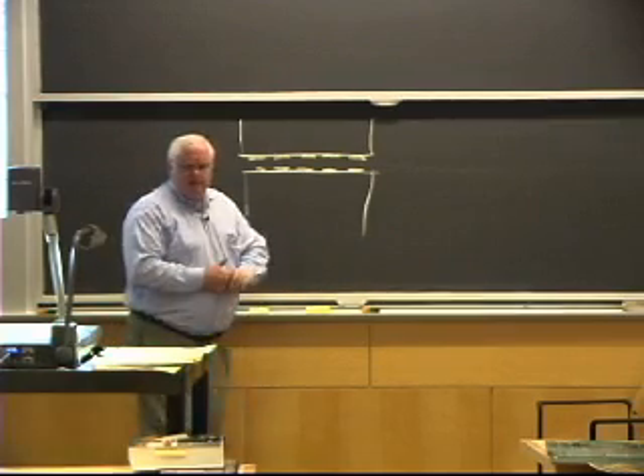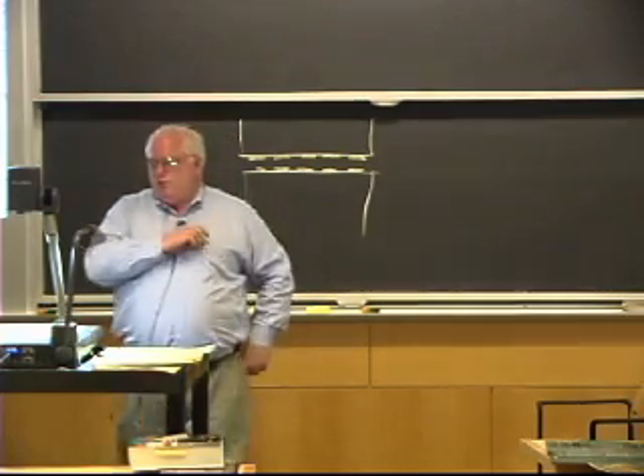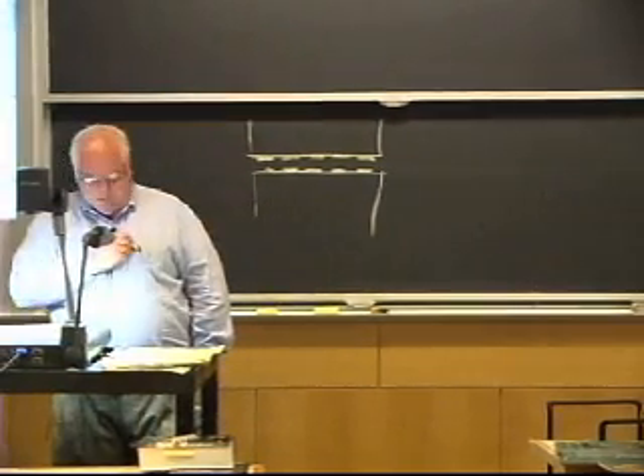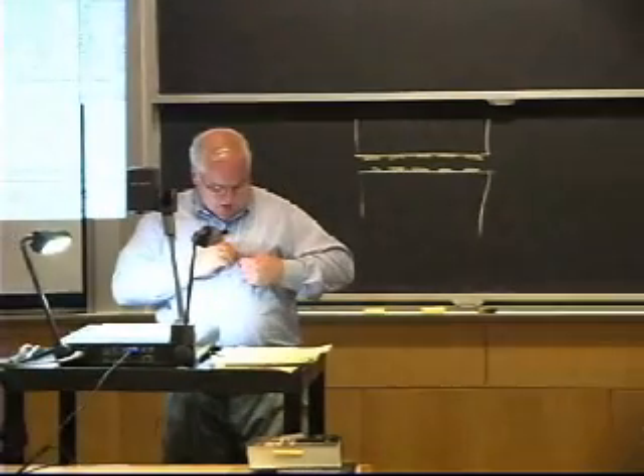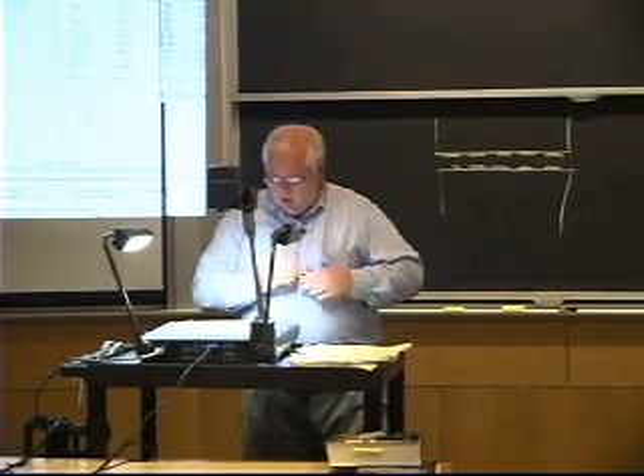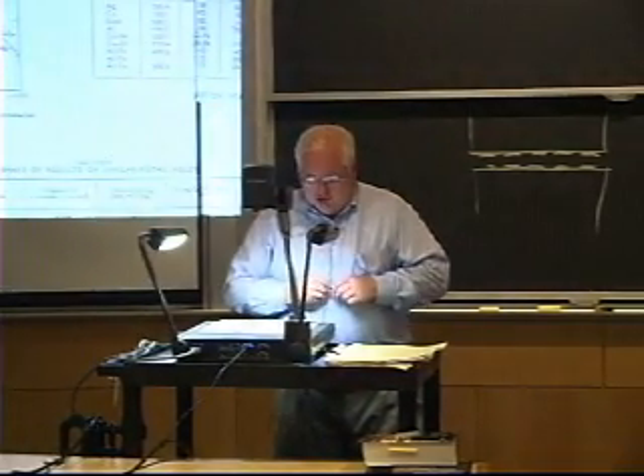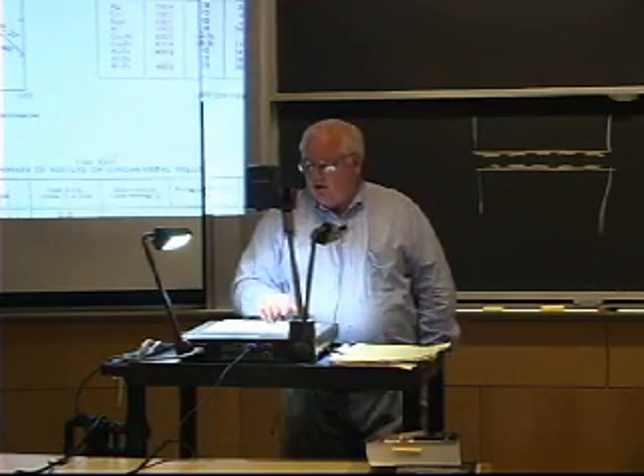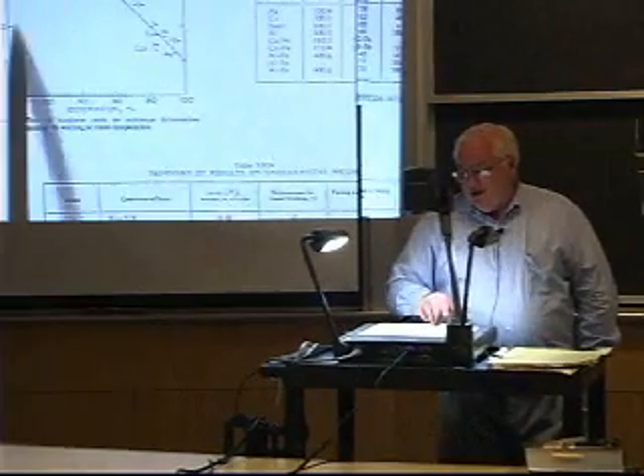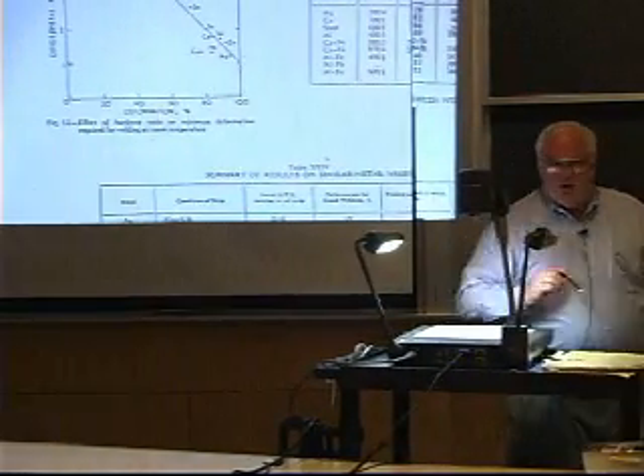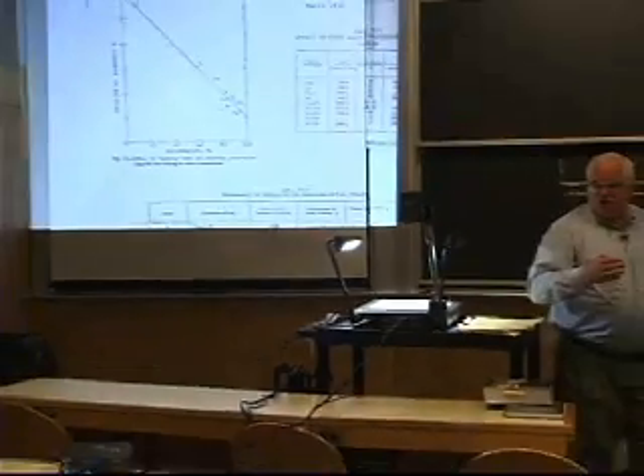So it turns out that it's a fairly simple relationship here of oxide to metal hardness ratio versus the percent deformation to form a cold bond, but it works out very well. Indium with only about 10% deformation can give a relatively strong joint.